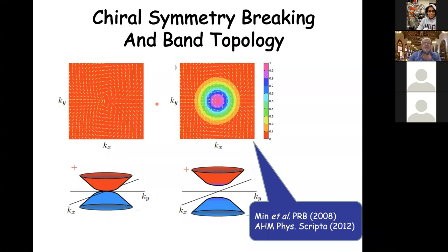And so in bilayer graphene, partly for this reason, there's a tendency for exchange interactions, which don't like the states to change rapidly with momentum. I think you're mostly familiar with the idea that's responsible for magnetism in metals, that exchange interactions like spins to be parallel. They also like, for the same reason, these layer pseudospins represented by these arrows to be similar to each other, to have a low energy state. They don't like them to change rapidly with momentum.